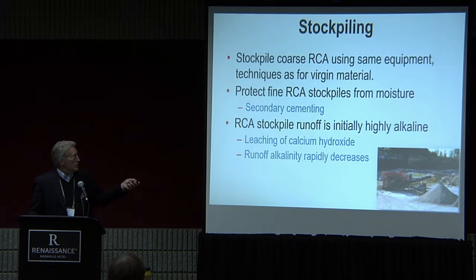And with any recycled concrete aggregate stockpile, the runoff initially is going to tend to be fairly alkaline. Okay, that same calcium hydroxide leaching process I told you about before. Until that stuff has been leached out and dissolved out of the surface of those aggregate particles, you may see runoff pH that's up in the 11, 12, 13 area. Okay, pretty high pH. So you want to collect that and not let that run off where it may cause an environmental issue. That does tend to decrease again as you consume the calcium hydroxide. That will stop and go away.